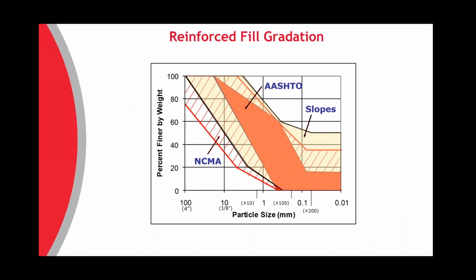So let's look at reinforced fill gradations. The requirements are going to vary depending on the design method that you use. Most DOTs are going to require an AASHTO design methodology. You'll notice here that the fine content, or the amount of fine materials less than 200 sieve, is 0 to 15%. The NCMA is used more for private commercial type work, and you'll notice the fine content there can go from 0 to 35%. Slopes can go up to 50% of fines, and that's why those sometimes are the least expensive grade separation system that you can use.